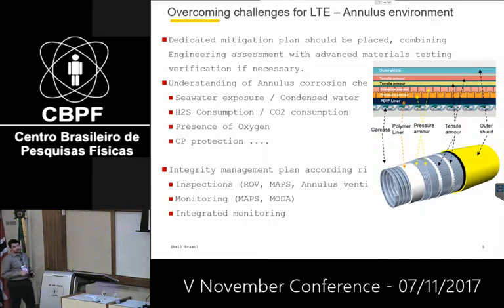We know that H2S consumption is very fast. A lot of papers published already show that the models are very conservative, but the CO2 consumption is something that we are still discussing, mainly if you have a very high partial pressure of CO2, maybe it cannot be consumed totally as we have with H2S consumption, but there are some chemistry in the CO2 that should be taken into account. Other things like presence of oxygen and cathodic protection. So a lot of complicated things that you should put in the testing, and you should overcome how to address all these things.